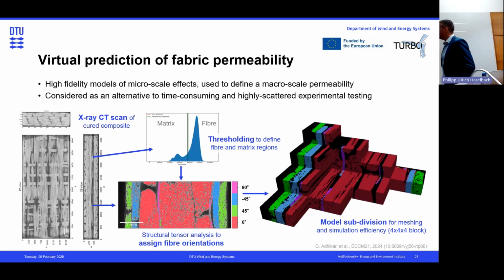Another way, of course, is doing a virtual prediction of fabrics, where you can do an X-ray scan of your material, and from that try to predict the permeability. And we have done so. We have also done virtual prediction where we just model the fabrics. So basically, we have three tools: our experimental characterization, the virtual prediction due to X-ray scan, and then the modeling aspect. And we could see when we compared all three methods on the most current materials that we use, it matches quite well. And that's, of course, important, and we have more confidence in the material input parameters that we need for our simulation.